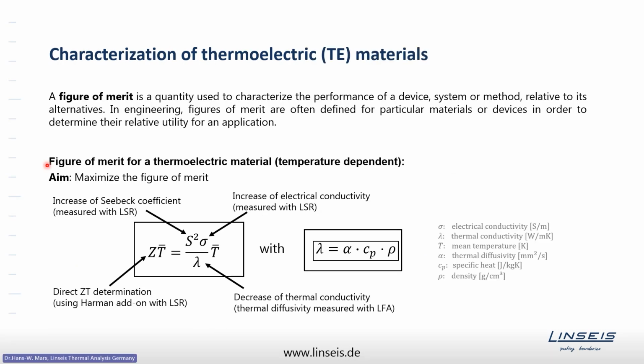So in general, to characterize the performance of a device, system, or method, the so-called figure of merit is defined. This figure of merit allows to compare the relative utility of a device or material for a certain application. It's defined for thermoelectrics as the figure of merit equals the Seebeck coefficient squared, multiplied with the electric conductivity and divided by the thermal conductivity. So the aim to have a powerful material with a high figure of merit is to increase the Seebeck coefficient, to increase the electric conductivity, and to decrease the thermal conductivity.